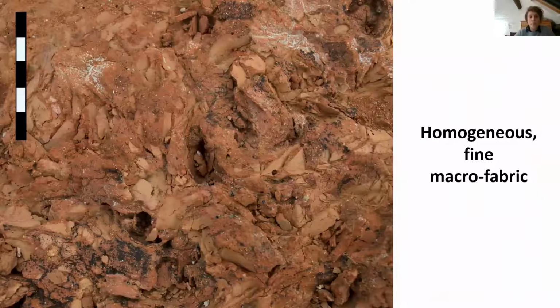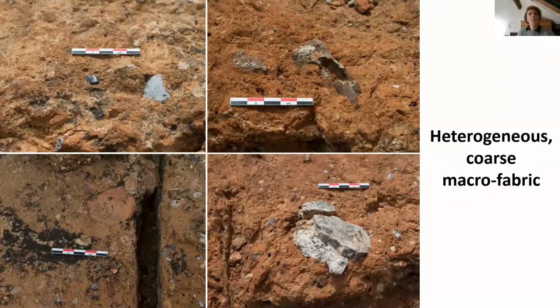Observation of the mudbricks used in the walls of the palace at Malia has shown that their macroscopic fabric composition, which means that is visible to the naked eye, range from fine to coarse. Mudbricks with a homogeneous fine macro fabric are usually reddish in color and are produced with a screened sediment with a maximum gravel size of 1.5 centimeters. These sediments are mixed with large quantities of marine seagrasses, and contain minimal other inclusions. Mudbricks with a heterogeneous coarse macrofabric are more varied in color and are manufactured with sediments which have not been screened so that they present numerous large inclusions, such as large gravels, obsidian, bones, shells, plaster, or ceramic fragments. It is also striking that the macrofabric of these coarse mudbricks present fewer seagrasses than the fine ones.